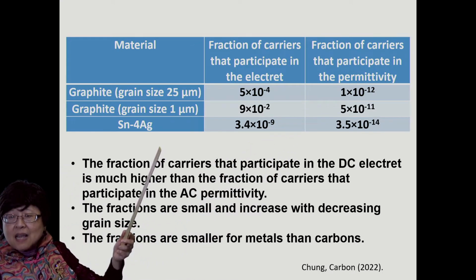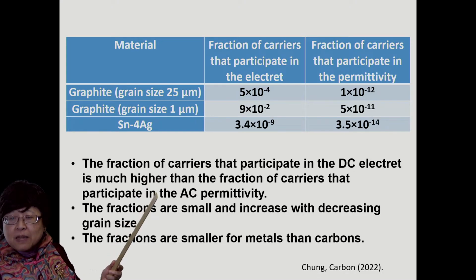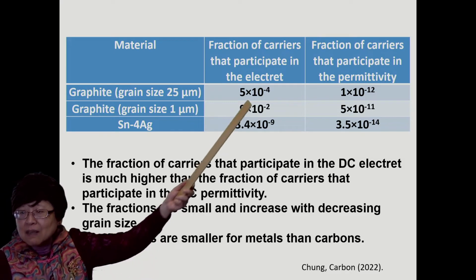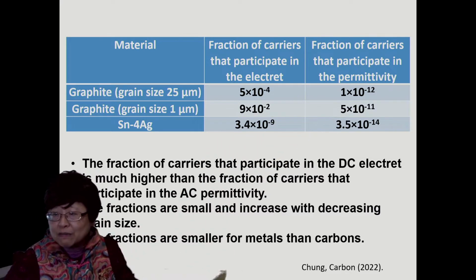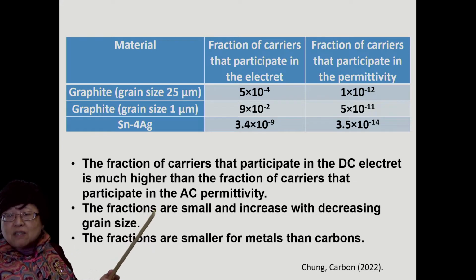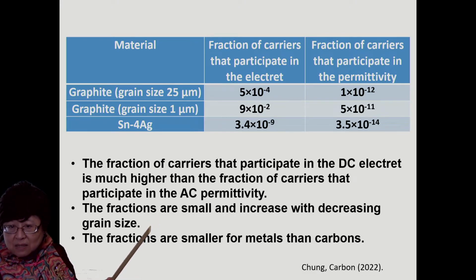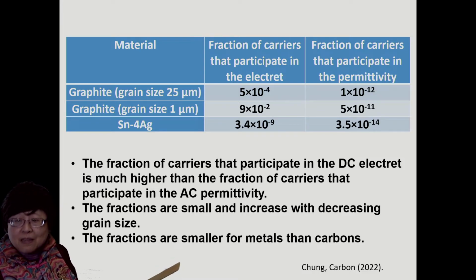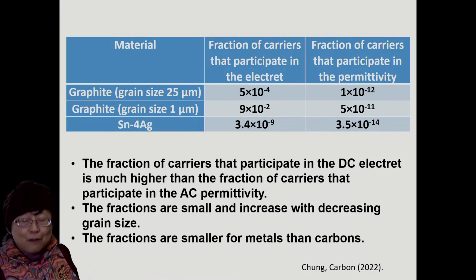And one finds that the fraction of carriers that participate in the electret is much higher than the fraction of carriers that participate in the permittivity. Okay, 10^-4 versus 10^-12, for instance. Also, the fractions are small, whichever fraction, and either fraction increases with decreasing grain size. And the fractions are smaller for metals than carbons because metals have a lot of free electrons.